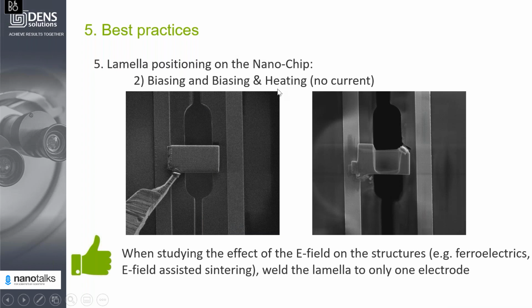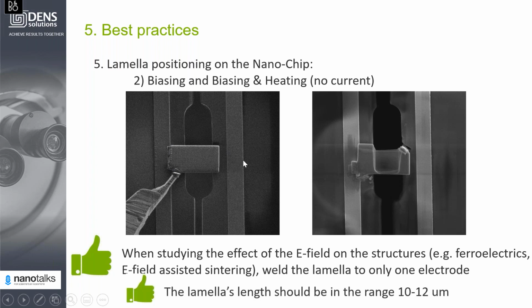For biasing and heating samples, where you don't want to actually measure any current, but instead you want to see the effect of electric field on the structure, for example, you want to study ferroelectric domains, or you want to see electric field assisted sintering, you can just weld the lamella on one side. Just because you don't need to have the second electrode connected. And in this case, the lamella length can be just in the range of 10 to 12 microns to position it between the closest inner electrodes.